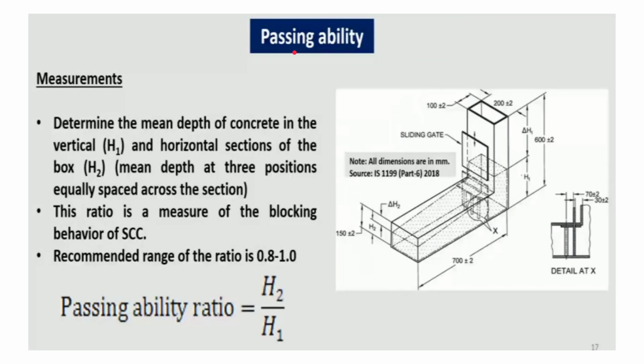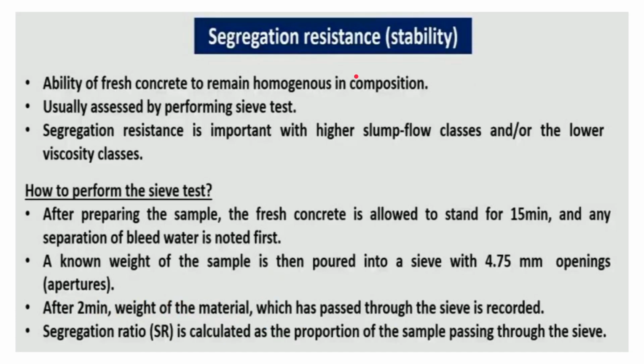So we have gone through the flowability test, which is done by the slump flow test. Then we have gone through passing ability, which is done by the L box test, for checking segregation through congested reinforcement flow. Now we shall come to segregation stability testing, again for segregation resistance. This is the ability of fresh concrete to remain homogeneous in composition. It is usually assessed by performing sieve tests. Segregation resistance is important with higher slump flow classes and or the lower viscosity classes.